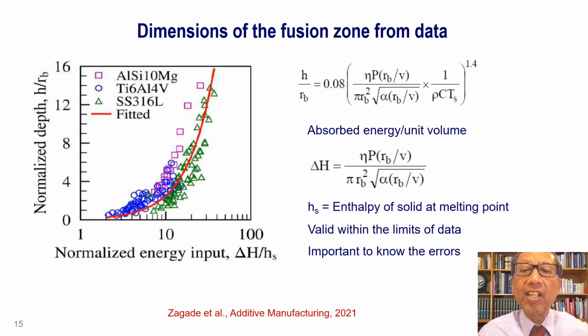The dimensions of the fusion zone are obtained from a model that is built by fitting data. The depth of the fusion zone divided by the radius of the beam is plotted on the y-axis, and on the x-axis we are plotting the normalized energy input. So what is that? Delta H here is the absorbed energy per unit volume, and Hs is the enthalpy of solid at the melting point.